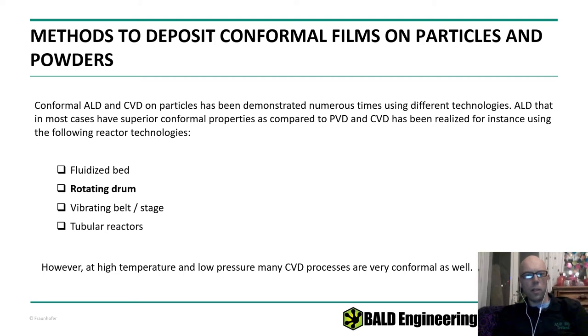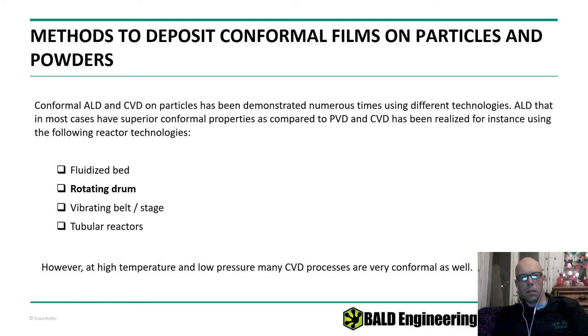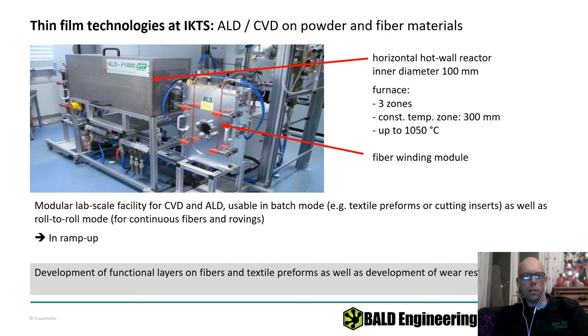I'll explain in more detail why and how it's integrated. There are other technologies too — if you want to scale up to metric tons, you might want a vibrating belt reactor or a spatial-type fluidized bed reactor. But the rotating drum is very versatile and can be easily integrated into a standard LP-CVD or ALD furnace, which is what we did.